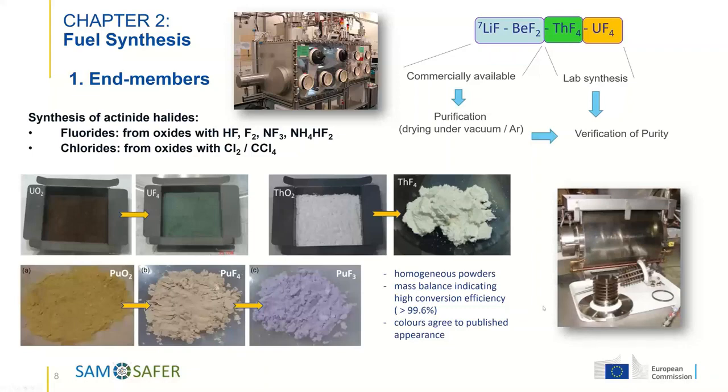So this is in principle the procedure. And for chlorides, we are using a mixture of chlorine gas with CCl4. It must be carbochlorination; the direct chlorination doesn't work efficiently. So those are the 2 things which we do. So that's for the synthesis.